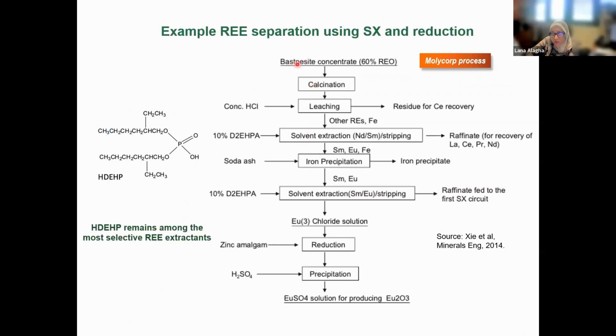This is the hydrometallurgical processing of bastnasite concentrate that contains 60% rare earth oxides using solvent extraction and then selective reduction. It starts with a calcination, then leaching in concentrated HCl to remove cerium. And then the supernatant goes to many stages of solvent extraction. The first is to separate heavier and lighter rare earth, and then iron precipitation to remove iron using soda ash, and then application of D2EHPA again. So D2EHPA is utilized here as an extractant in kerosene.